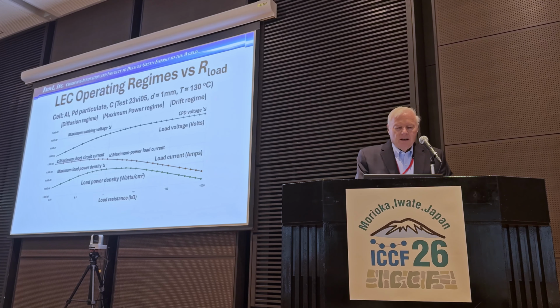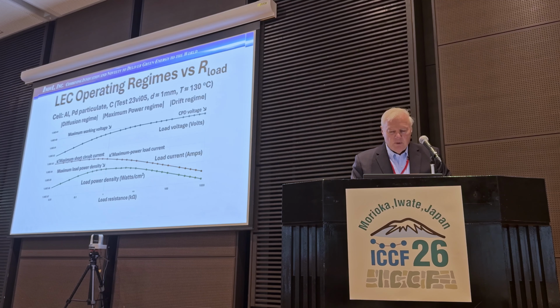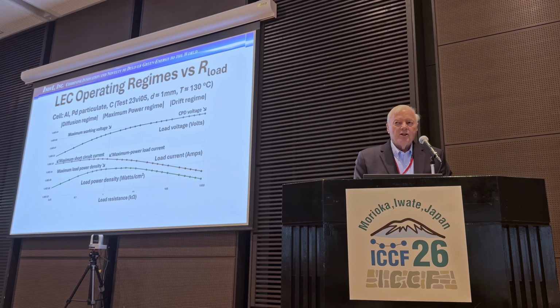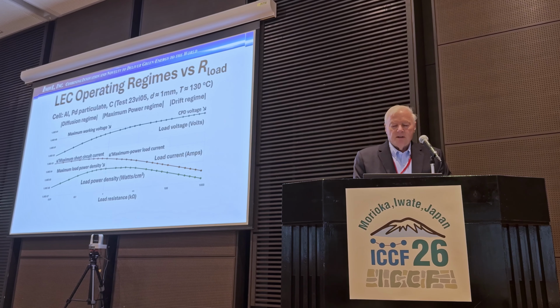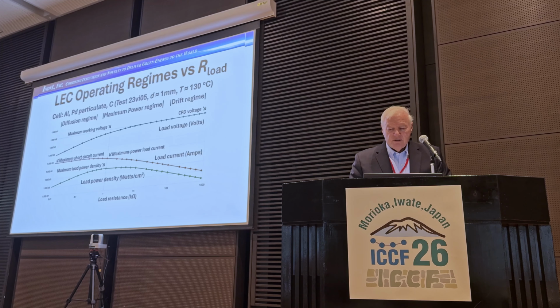This shows a typical test, the operating regime, and what you see here is the voltage. Across the bottom, we have load resistance. So if we start out with real high voltage or high resistance, we get the high voltage. Basically, what we're measuring at this point is close to the work function difference between the electrodes. As we reduce the resistance, we're actually increasing the load on the cell. And when we get down to the low, say 10 ohms, we're producing the maximum short circuit current. But at that point, the voltage is very low, and so the power is very low. So anyhow, I'll mention this again later, but it ends up being a safe device. And the maximum power output is at kind of the midpoint between the diffusion and the drift of the ions in the gas.